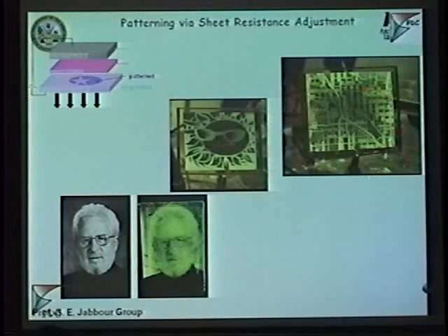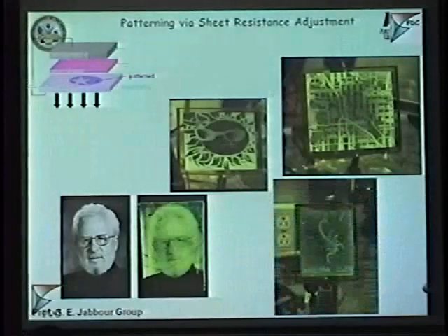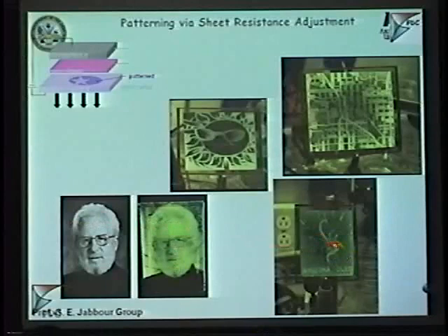But you could see that you could get extremely good resolution with this, and we have done this in infrared as well for security reasons, and that also is reproducible. You could see the grayscale with the dark hair that is left on the beard here, the suntan is reproduced, and also the scorpion back, which is really grayscale, reproduced very easily. And you can see also the dust particles here from the spin coating of the light emitting polymer. So in all of these, the image was printed with the inkjet.